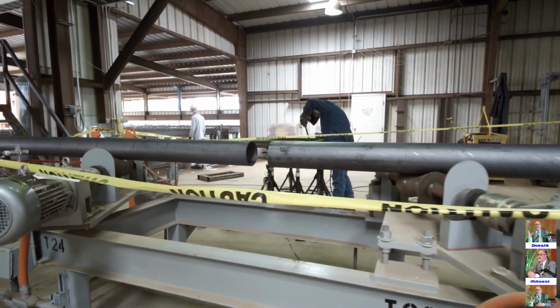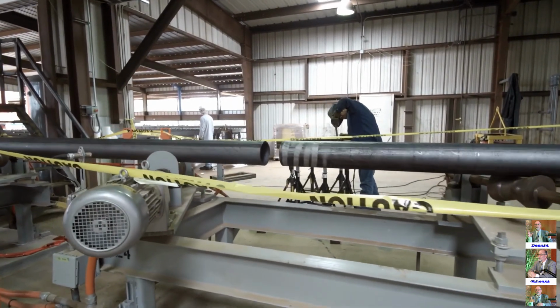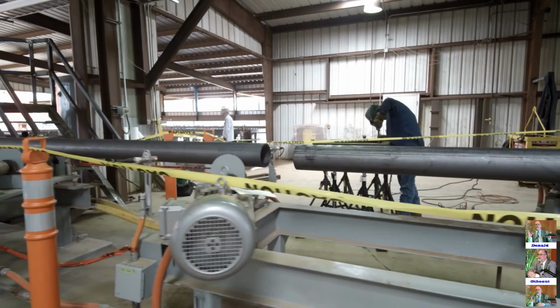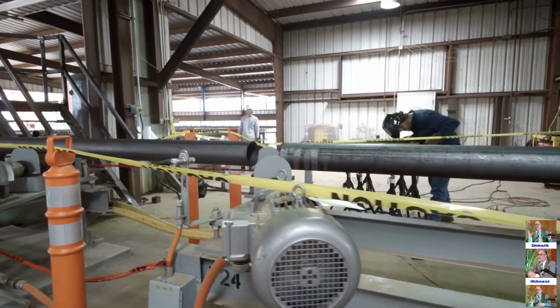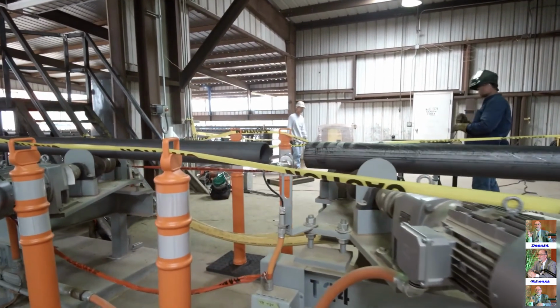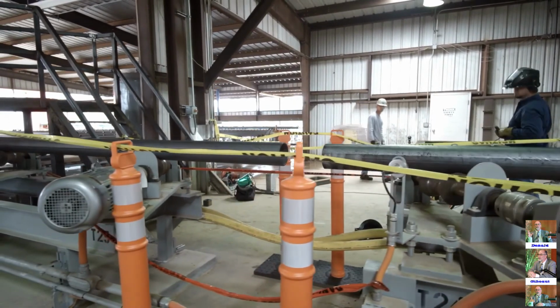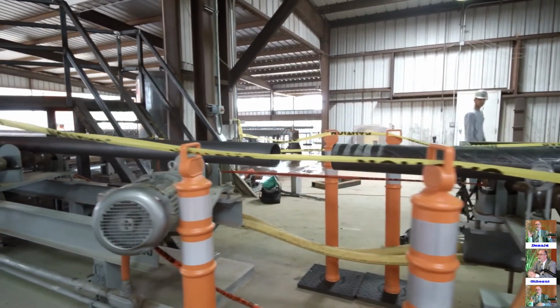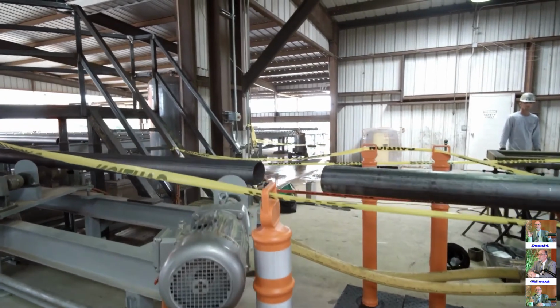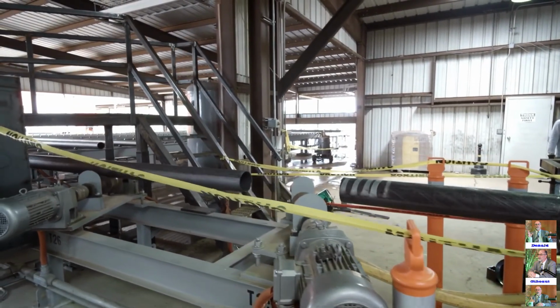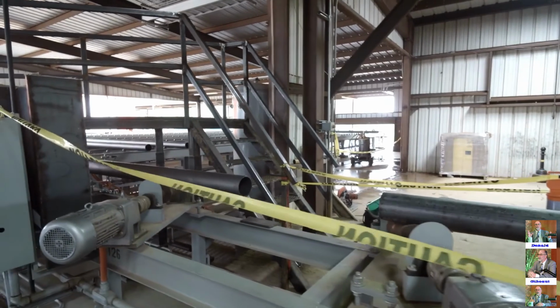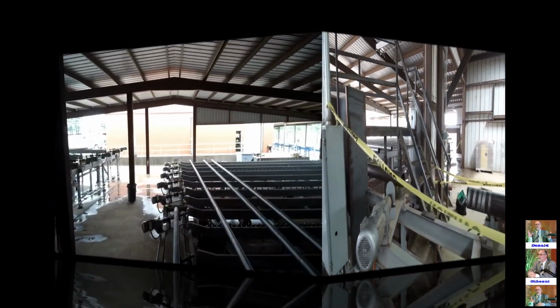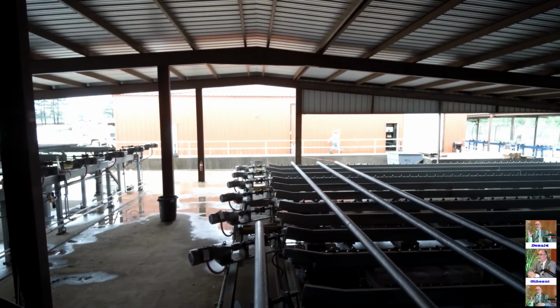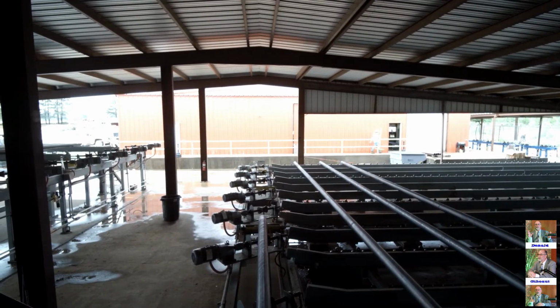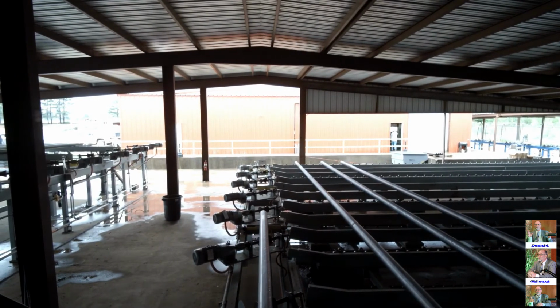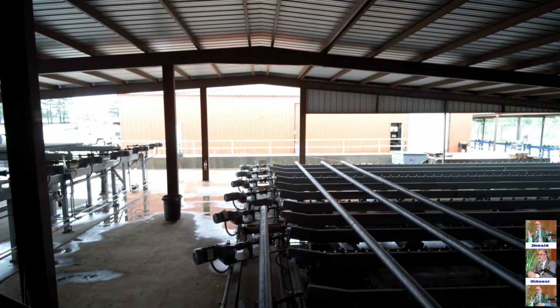The photo eyes identified the front end of this pipe, and it identified the back end here, and then it starts separating. As you get smaller lengths of pipe, this separation happens a lot more rapid. It'll drive this pipe forward a lot quicker so it can get to the end stop, so then the paddles can transfer it over to the cooling bed. But you can see there it really starts separating pretty good. Here's the pipe exiting on the rolls prior to the cooling bed.